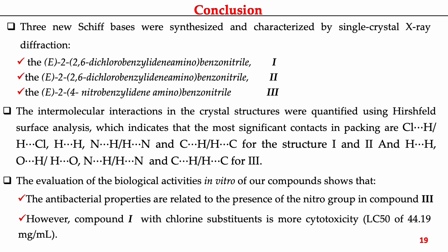In conclusion, 3 new Schiff bases were prepared and characterized by single crystal X-ray diffraction. The intermolecular interactions in the crystal structures were quantified using Hirschfeld surface analysis, which indicates that the most significant contacts are Cl...H, H...H, N...H, and C...H for compounds 1 and 2, and H...H, O...H, N...H, and C...H for compound 3. The evaluation of the biological activity of our compounds shows that the antibacterial properties are related to the presence of the nitro group in compound 3. However, compound 1 with chlorine atoms is more cytotoxic.